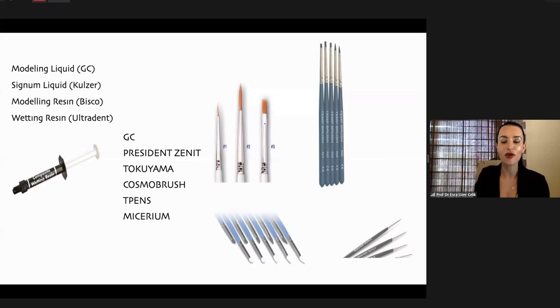You shouldn't use adhesive between unpolymerized composite layers because adhesive systems include solvents, and you have to remove the solvents after the application. If the composite resin is unpolymerized, you cannot remove them by air drying because it will destroy the composite surface. In that case, there will be some bubbles, some gas between your composite layers. So between unpolymerized composite resin, we strictly advise using just modeling resins, and use little amounts of this material. Just wet the brush, because large amounts can negatively affect the surface hardness of your composite resin. Be careful. Just wet your brush. It's enough.